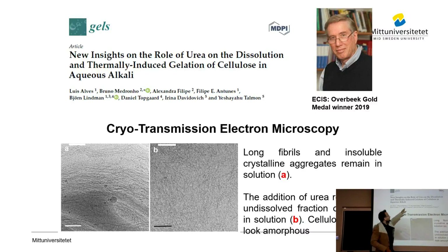And here we were also interested in the role of urea, an additive that we very often use to improve the dissolution. Urea is known to break hydrophobic interactions, for instance in proteins, so it's also used to break the hydrophobic interactions in cellulose, so it makes all the sense. And we observed that with urea, the dissolution was better, it facilitates it. We don't see that many aggregates in solution, and the long fibers that we see when we don't have urea. So this was perhaps the first time, at least to my knowledge, that we could really visualize an effect of this additive, urea.